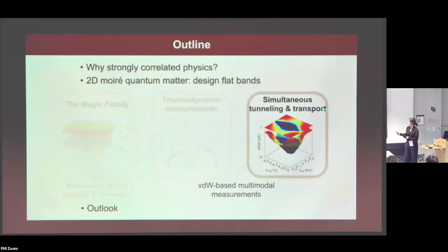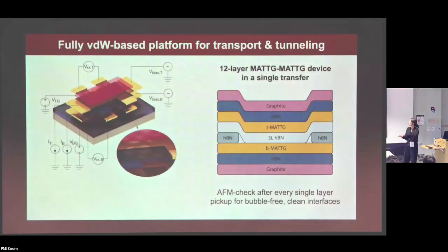And so there goes the second part of this, the van der Waals-based multimodal measurement technique. Now this is our device structure. We have a 12-layer stack where you couple magic angle twisted trilayer graphene with another magic angle twisted trilayer graphene with a 3-layer thin tunnel barrier of hBN. That's a typical structure of a tunneling junction that you can think of.